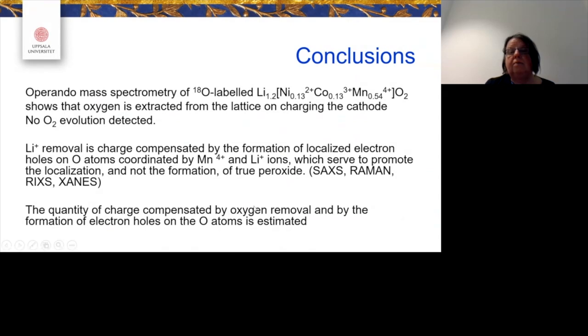So then to really build this conclusion, you need data from the SAXS, Raman, RIXS, XANES, etc. And we could even quantify the charge compensated by oxygen removal and by formation of electron holes on the oxygen atoms. And this, I think, is now almost one of my most cited papers, but I can tell you not everyone trusts these results. It's an ongoing debate.